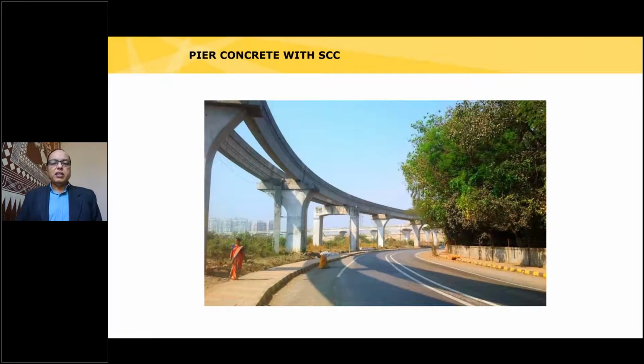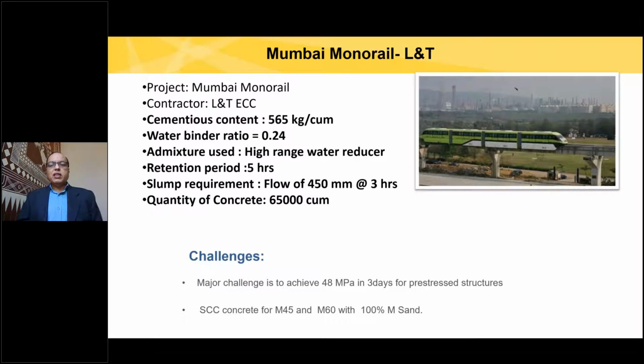Now, this is the finished structure, the Mumbai Mono Rail structure. Now, what were the concrete properties here? Please note, in this case, the cementitious content was 565. I repeat, it is not the cement content, it is the cement plus mineral admixture content, 565 kgs. And what is the water binder ratio? When you use other cementitious materials, you call it water binder ratio, not water cement ratio. Water binder ratio is so low, 0.24 was the water binder ratio.